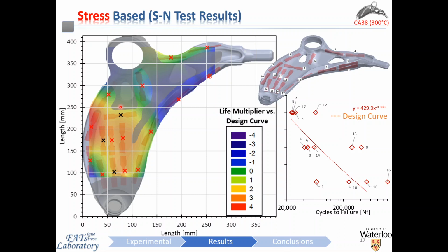It can be seen that in location 1, near this region of the line here, a location which is a topic of further discussion in another presentation actually in this virtual conference, it has the lowest life multiplier with a life that's over 4 times less than the idealized behavior. Whereas location 9 on the other side of the arm shows kind of the converse effect, where the design curve is conservative in its fatigue prediction.